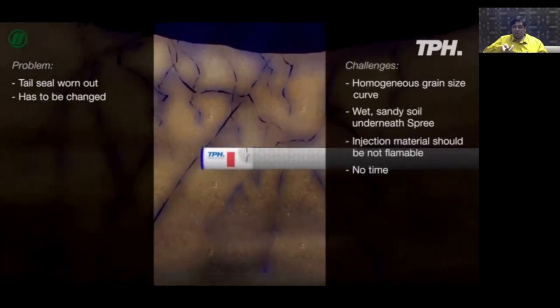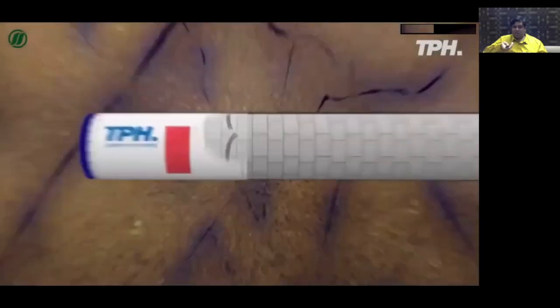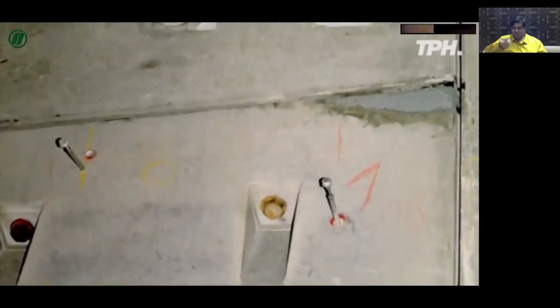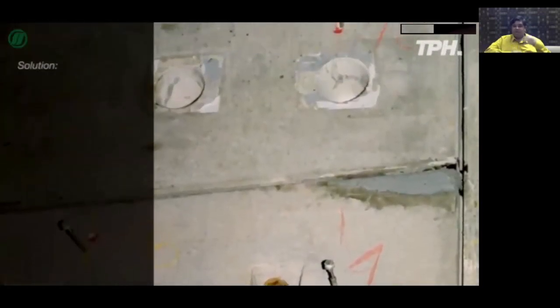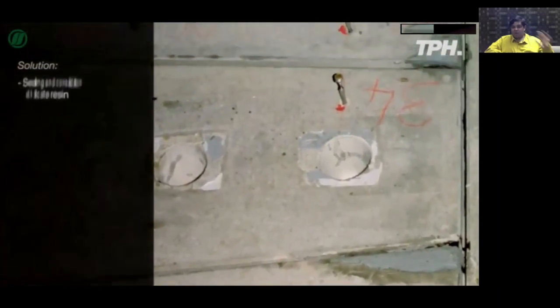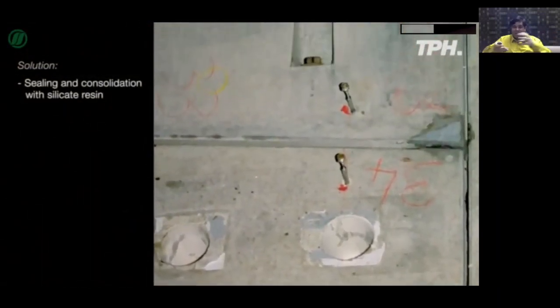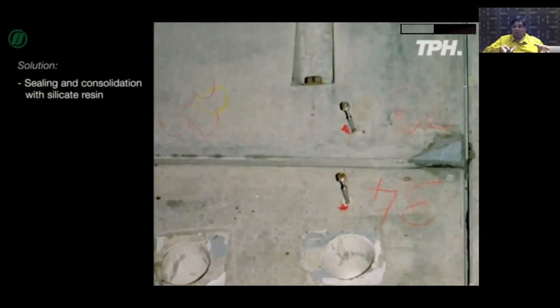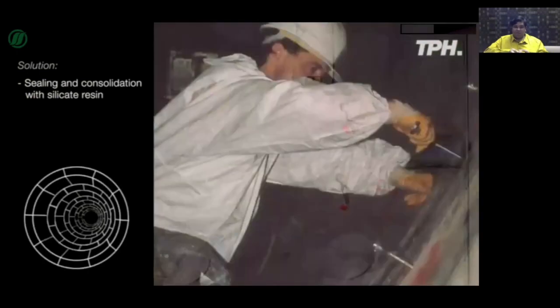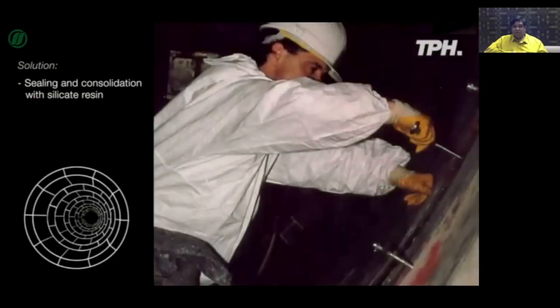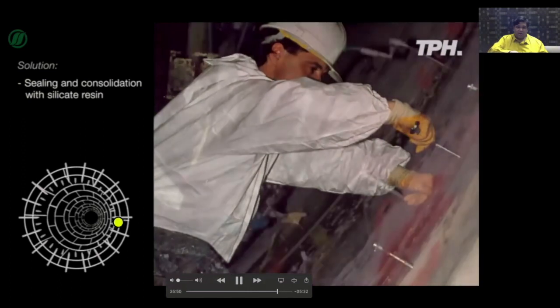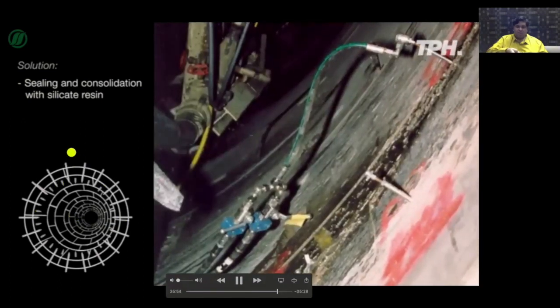Some of the challenges you can see here: the soil conditions, limited space, and they had to do a quick turnaround because the TBM can't be standing in one place for a long time. But the TBM could not move forward until the tail seal had been fixed. So in this case, the sealing and consolidation was done with a silicate resin. Again, a grid was created along the tunnel face from the inside to the outside, and the silicate foam was injected.